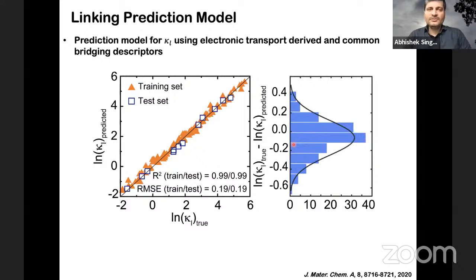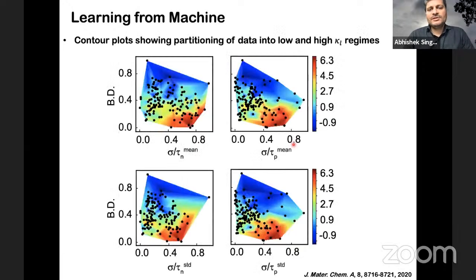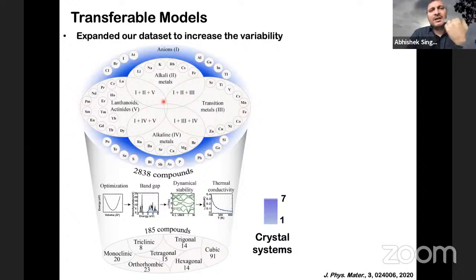So this was probably the first time where we have connected something which is completely unconnected. Electronic transport and thermal transport, which are not connected, can be connected by using machine learning. Of course, learning from machines. So here what we found is that if you know bond distance and sigma, for example, these two, very easily you can tell which compounds will have a lower thermal conductivity and which kind of compounds will have a higher thermal conductivity. We also looked at transferable models.